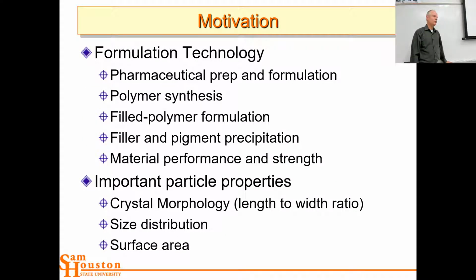This is related to formulation technology, so some of you may end up in pharmaceutical prep and formulation. And particle size and particle morphology have a lot to do with how you can press organic molecules into pellets, how stable those formulations are going to be, also bioavailability. So if it takes a certain amount of time to dissolve a particle in the stomach or in the small intestine, you want to match the particle size with that time constraint.